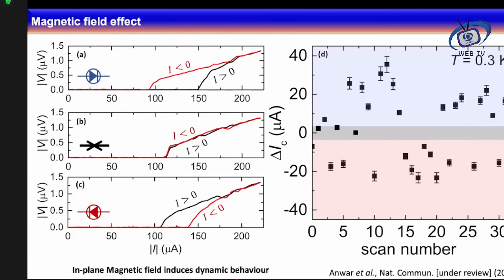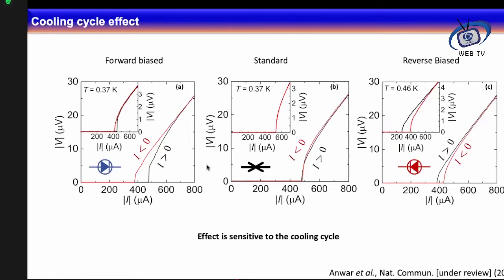And a similar effect was also observed if, for example, we have different cooling cycles. The cooling cycle means that you are in the superconducting state, then you warm up your system and you go to a relatively, let's say, 10 Kelvin, where it is completely out of the superconductivity.